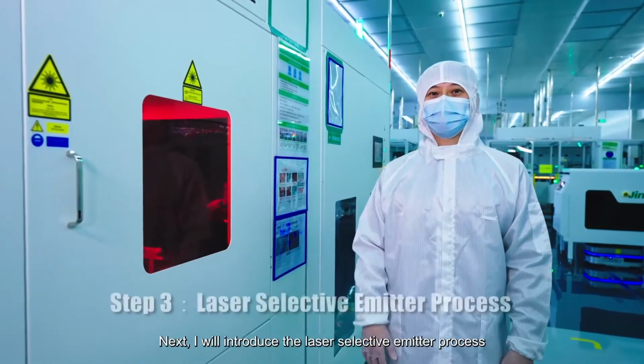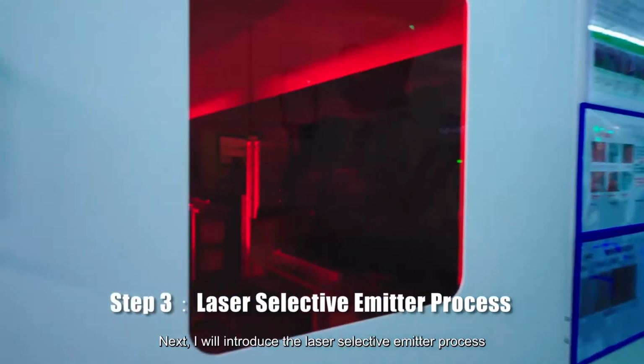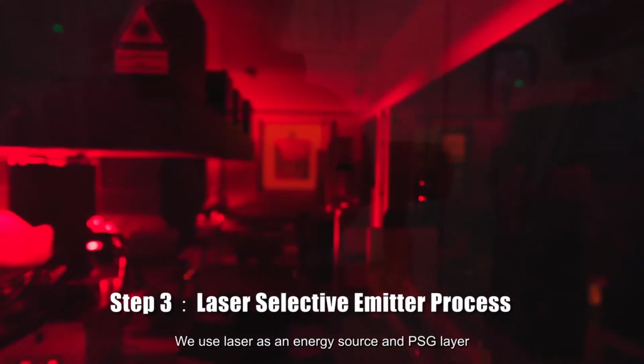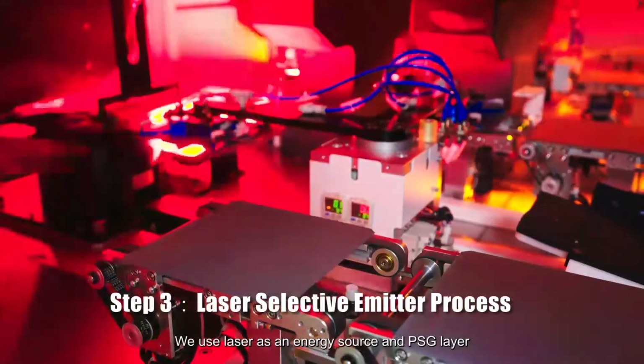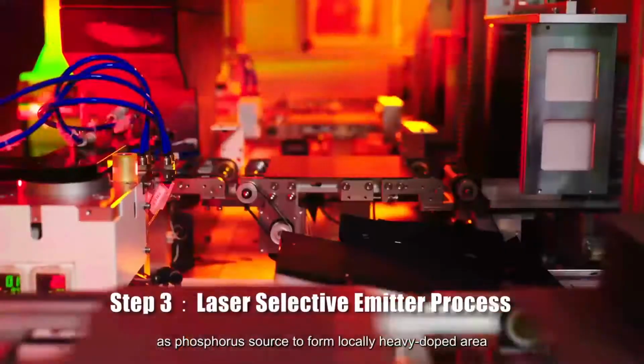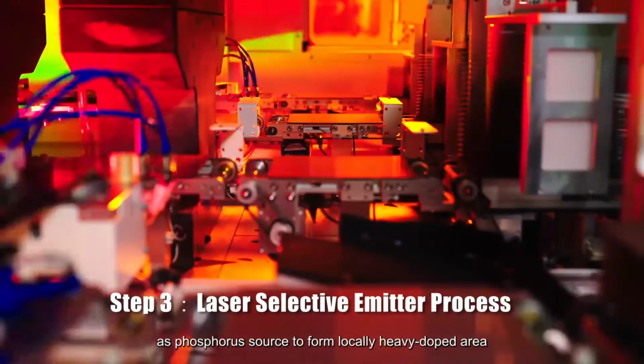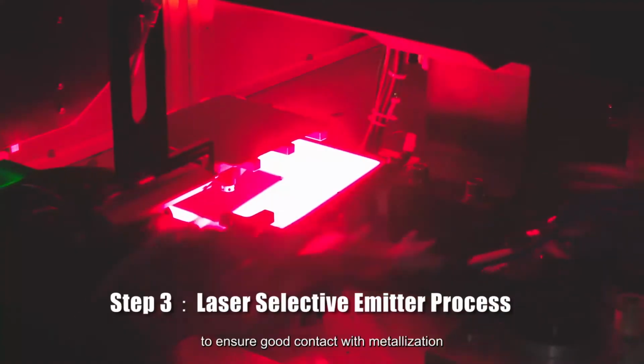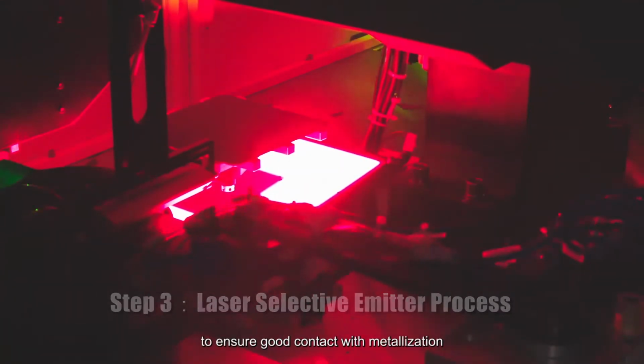Next, I will introduce the laser selective emitter process. We use laser as an energy source and the PSG layer as phosphorus source to form a locally heavy doped area to ensure good contact with metallization.